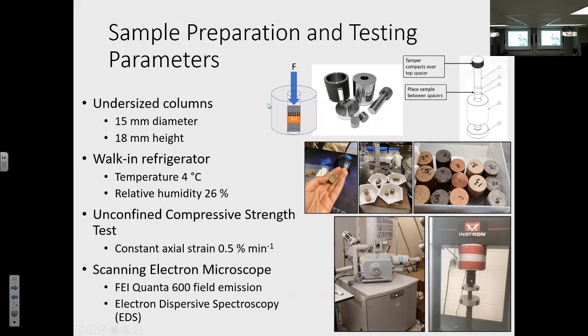And for testing, we took our samples to CIR at Texas A&M. I don't know if you've been there at the RELLIS campus. We used the Instron universal testing machine for our unconfined compressive strength test. Basically, it is a uniaxial force test. So you just have this huge frame that's constantly putting pressure on your sample, and you're trying to see when it breaks. When it breaks, it means it has gone through plastic deformation. So we're trying to find out what the maximum amount of force is that it takes to break our samples.